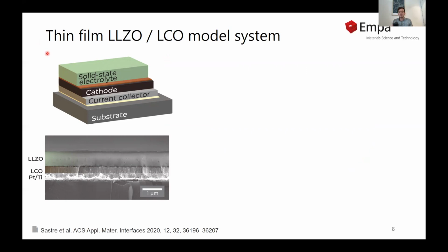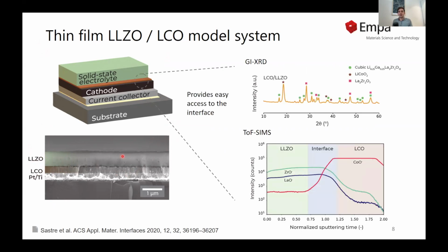Utilizing the thin film LLZO process previously described, we built then an LLZO-LCO model system in the form of thin films, which provide an easy access to the interface for characterization. For example, by grazing incidence XRD, we could characterize the phases of the decomposition products forming at the interface. Besides the LCO and the LLZO phase, we observed this lanthanum zirconate phase, which is a sign of degradation of